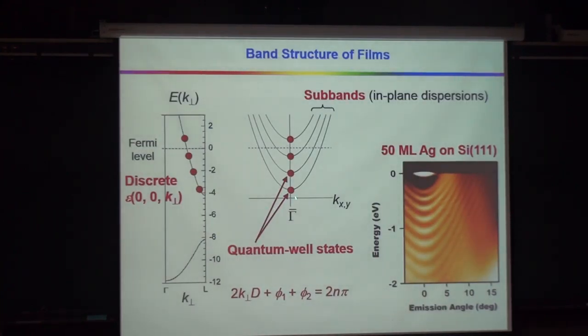I won't bother you with the details. But anyway, along the perpendicular direction, you get these quantized states. Of course, you can also measure the dispersion relationship in the plane by changing the angle. Typically it is a free-electron-like dispersion, so you have a whole bunch of parabolic dispersion relations. We call these subbands. Here is an actual example: 50 monolayers, ML, of silver on silicon 111. Instead of just one big blob, as you would get for a single crystal of silver, you see these discrete states just like pictured here.